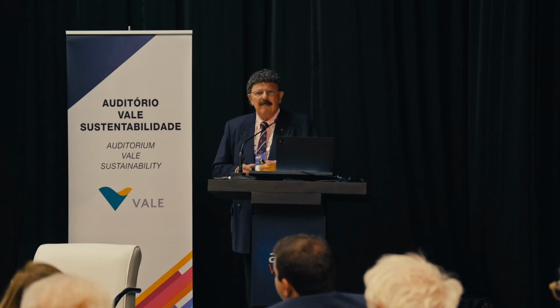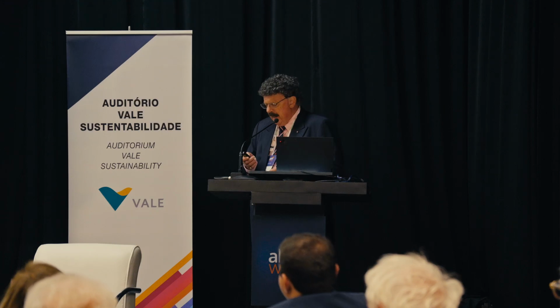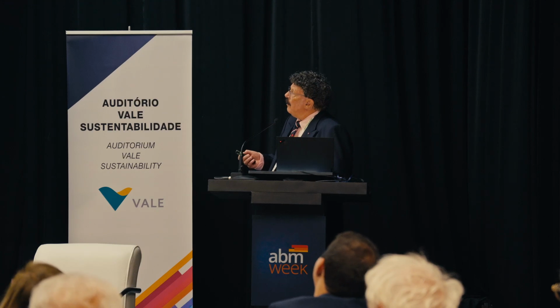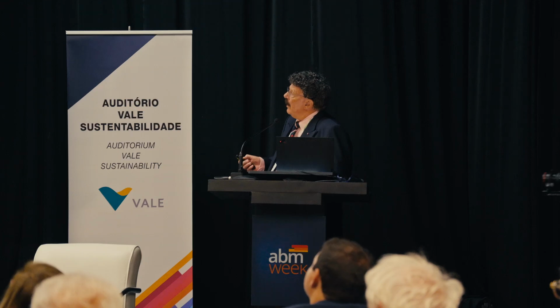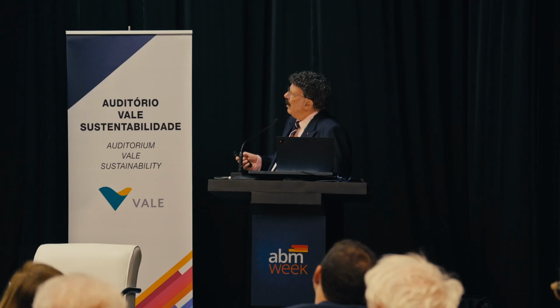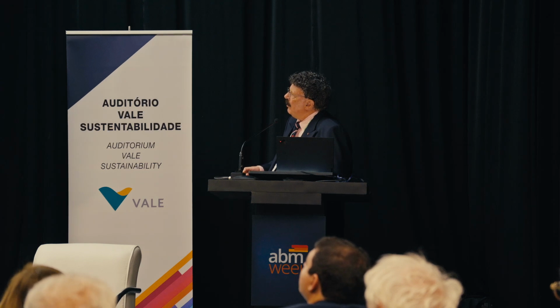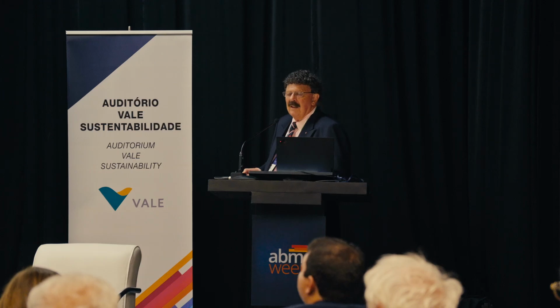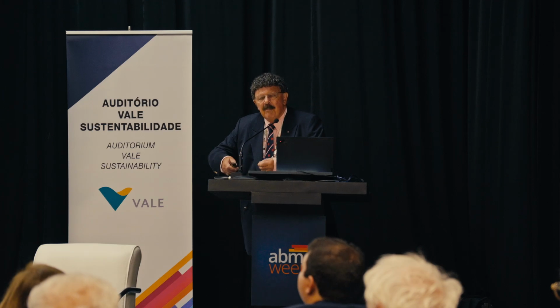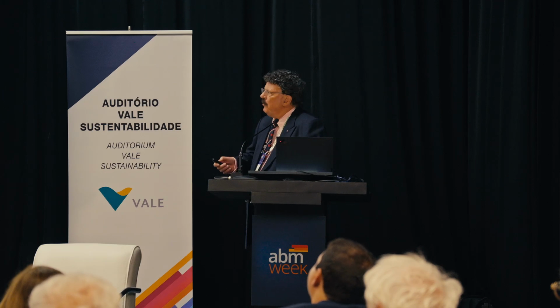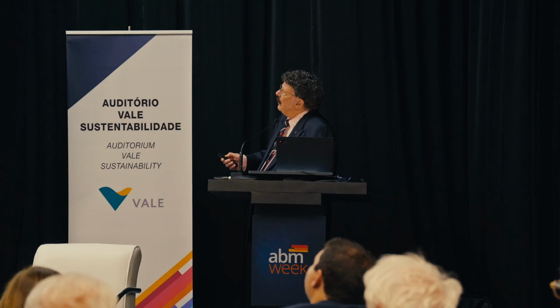We've looked at some other applications of these to try and make them better. This was using a material where we could get more of the transformation. It's called a dual phase material. It has some martensitic material within it: an austenite phase, FCC, and it has a bit of martensite in the middle. So that promotes the TRIP, the transformation-induced plasticity. And it's similar, it's simply a chrome, cobalt, nickel material.